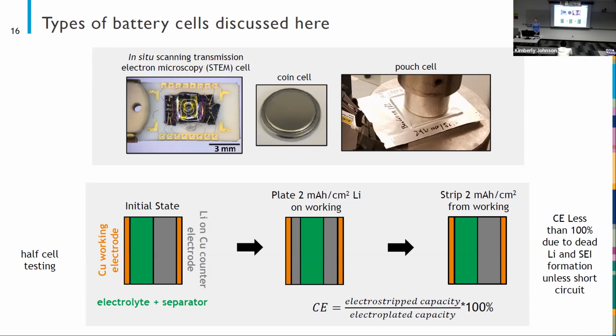Now, I'll be talking about what we refer to as half cell testing. These can also be called anodeless cells. And these cells in their initial state are built such that there's lithium on copper as our counter electrode. We have an electrolyte and a separator, and then we have a copper working electrode. And what we're going to be doing is plating a certain amount of lithium onto the working electrode from the counter electrode electrochemically. And then we're going to strip away that lithium and move it back from the working to the counter electrode. We measure the coulombic efficiency of that process. Like I mentioned, it's the amount that we're able to get back that we were initially plating onto the working electrode. And this is always less than 100%, or should be always less than 100%, because we have dead lithium formation and we have that SEI formation that occurs.